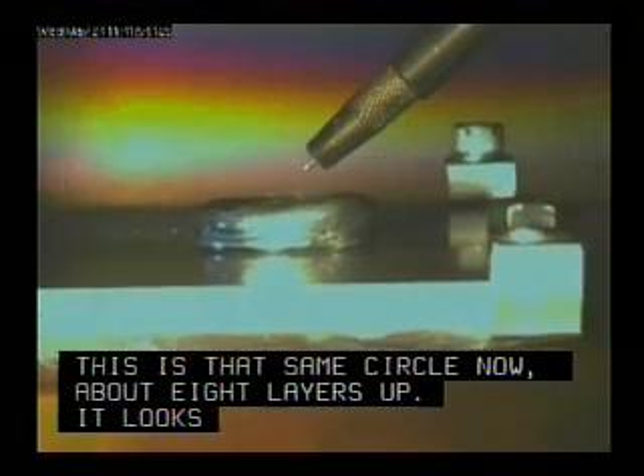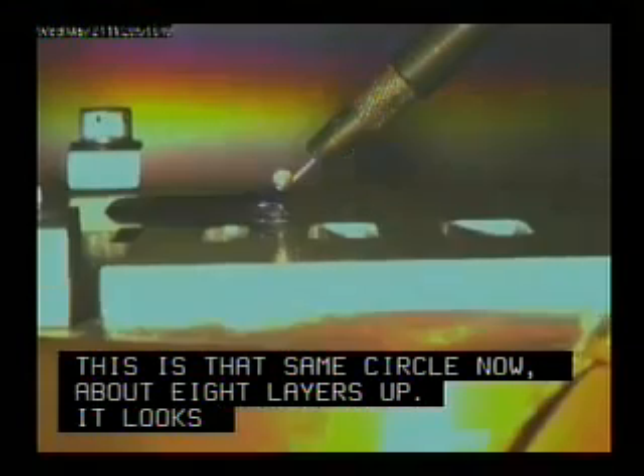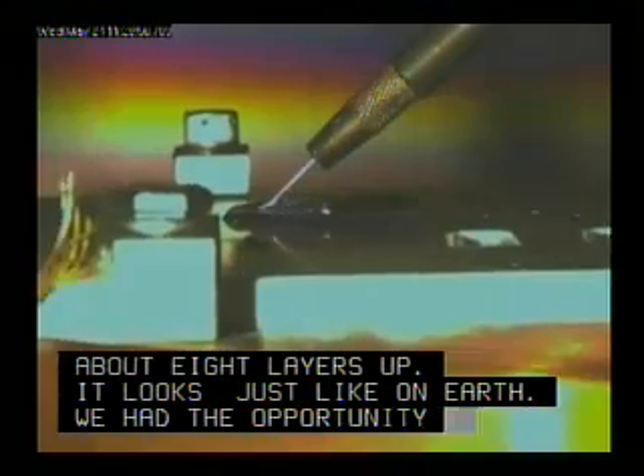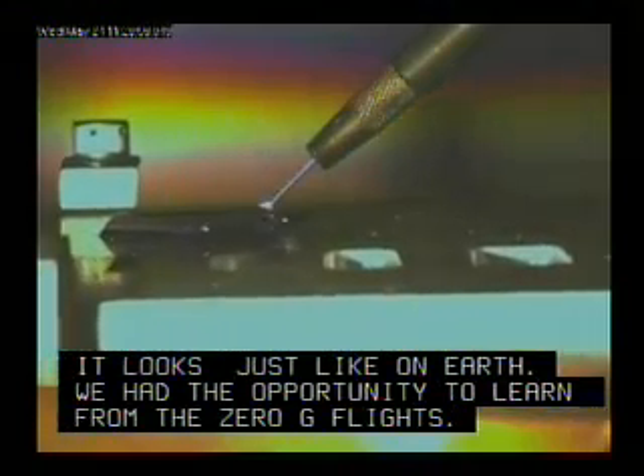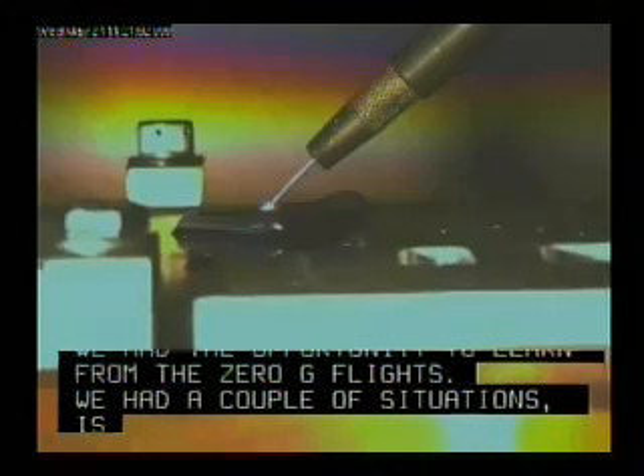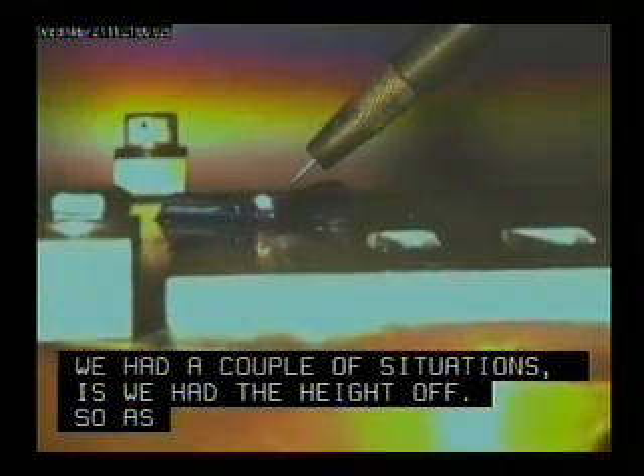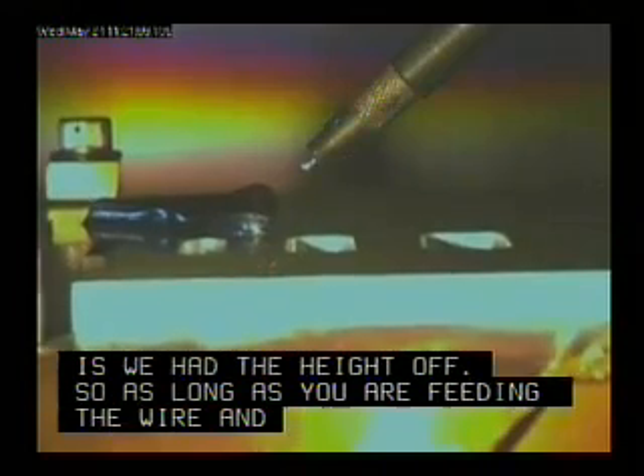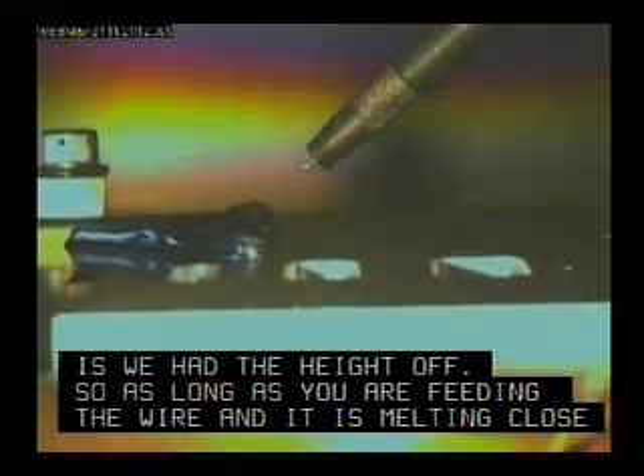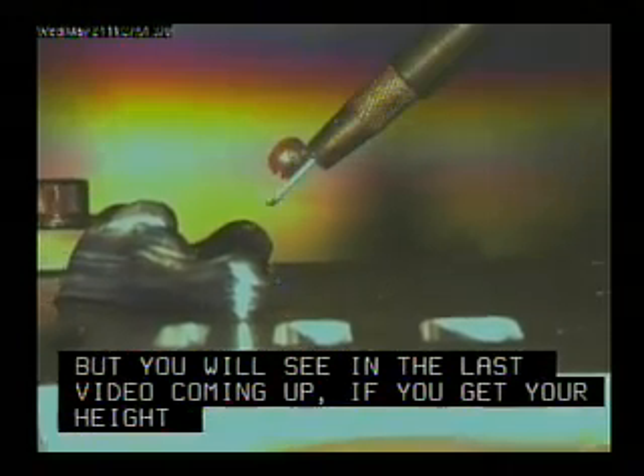We did have the opportunity to learn from the 0G flights. We had a couple of situations, and it's shown in these next 2 video clips, where we had the height off. As long as you're feeding the wire and the wire is melting close enough to the molten pool, close enough to the surface, everything adheres. But you'll see in the last video coming up that if you get your height off, things go bad in a hurry. You can see when we start separating from the molten pool, it just builds a bigger and bigger blob until we get close enough. What's encouraging about this is that the wetting forces do overcome the surface tension, so the process does work.